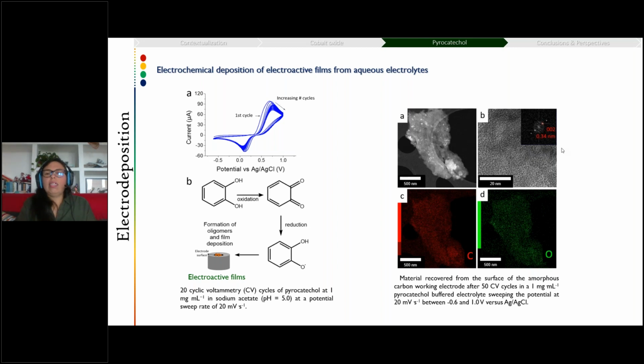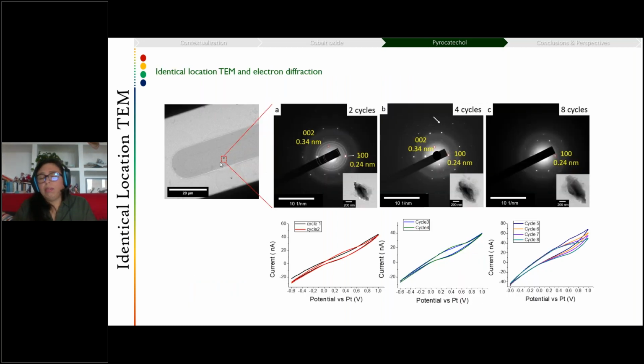So we used the electrochemical cell to electrodeposit the pyrocatechol. So we flow through our solution of pyrocatechol, and then we cycle the potential and see what was happening at each state. This is in dry conditions, so we remove the chip every time and observe what happened upon cycling. At the beginning, we right away observe the formation of a structure that has some crystalline regions, but there is a polycrystalline characteristic to it because we can see rings of this material.